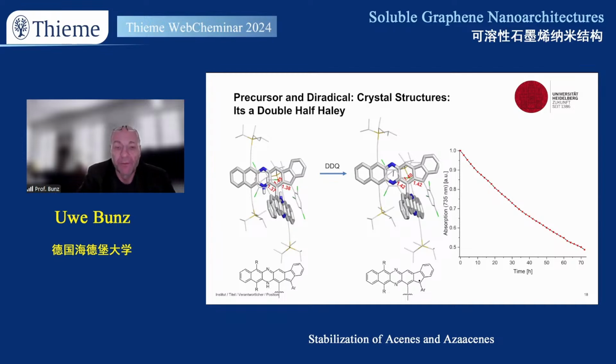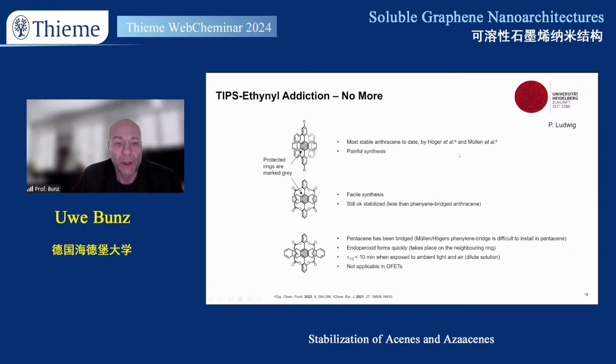that, using DDQ and heat, gives you the corresponding radical here. And a small detail to note here is that you have to use trichlorophenyl groups to stabilize this material here. Regular mesityl groups would not do the job in the sense that they would actually form decomposition products here. So this material here is stable, and then of course slowly decomposes.